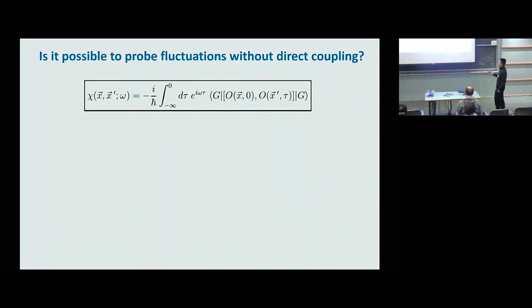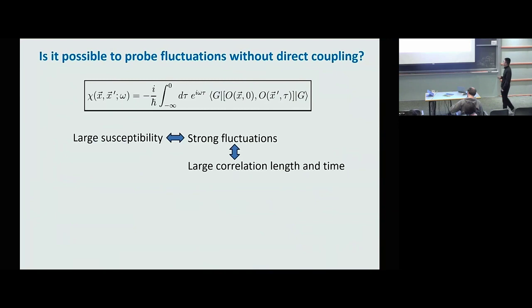The reason why susceptibility can be used to measure the strength of fluctuations is because of the fluctuation dissipation theorem or linear response theory. This tells us that when there's strong fluctuation of a certain order parameter, then if you drive it, the response will be very strong. It also tells us what strong means exactly here. If you have a strong fluctuation, it really means that there's a large correlation length and time of the fluctuation. And that can be intuitively understood because if the correlation time and length are long, then that means the response is contributed by the driving over a large length and time scale, which may make the response very large, which means a large susceptibility.